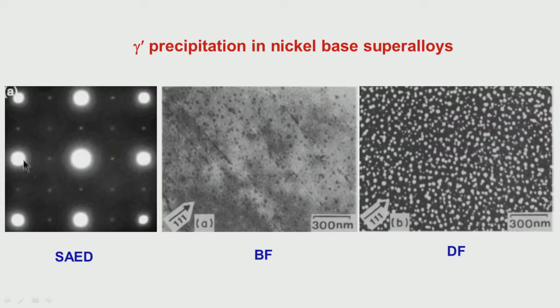What I am showing here is a diffraction pattern taken from gamma prime precipitates in nickel based super alloys. You can see the central spot and weak super lattice reflections. I put an aperture around the central spot and get an image, and this is the bright field image where we can see these dark regions are the precipitates. Now I put an aperture around this super lattice reflection. Now I can see the particles which are there and how they are distributed, their particle size, all this information which I can get.